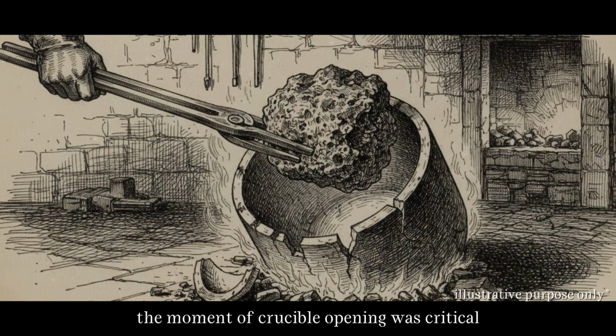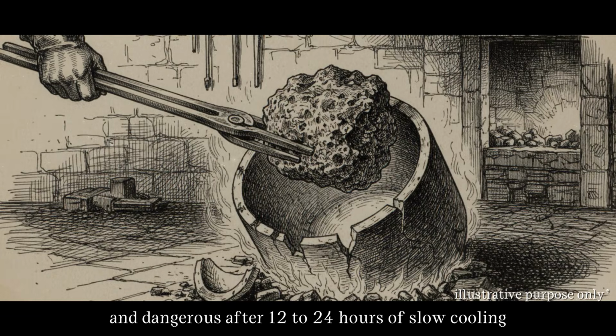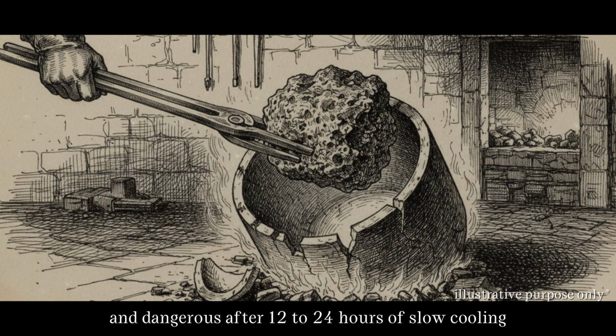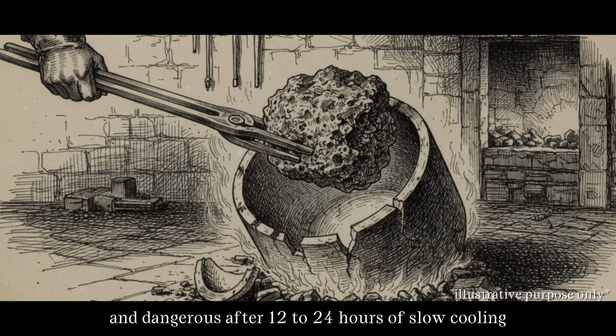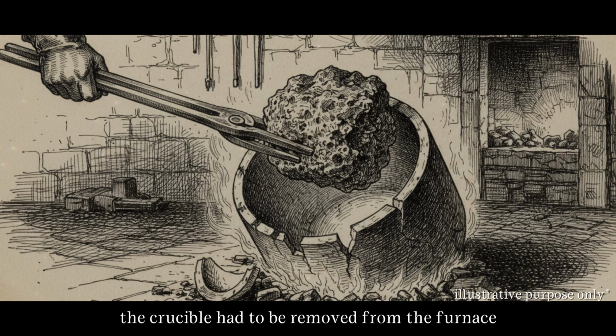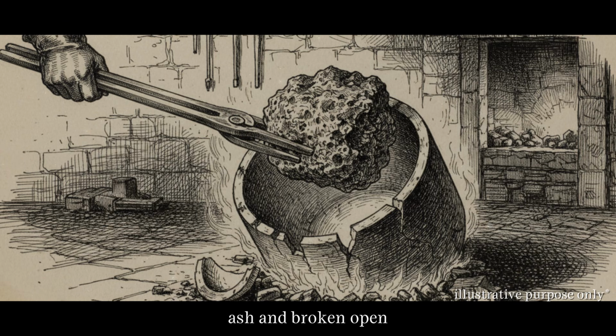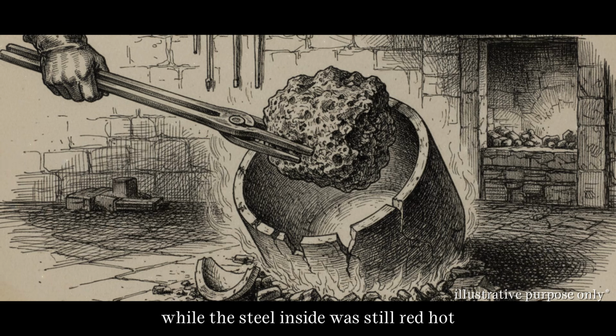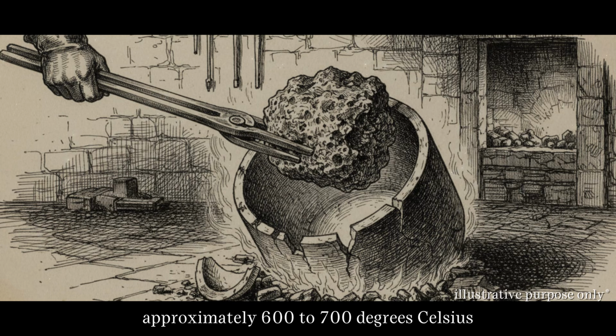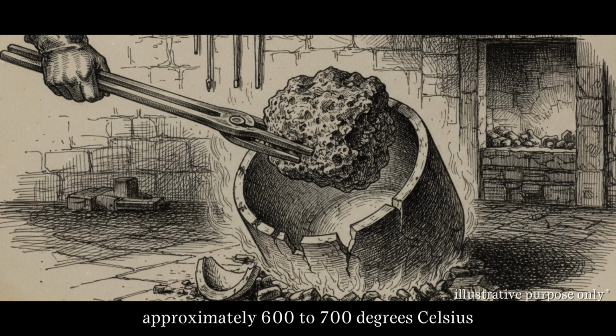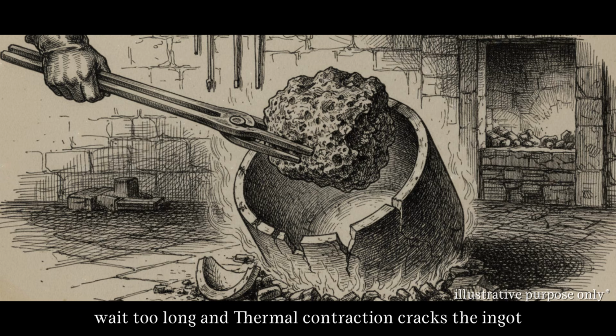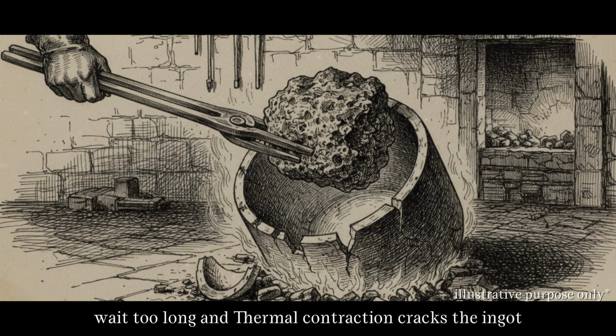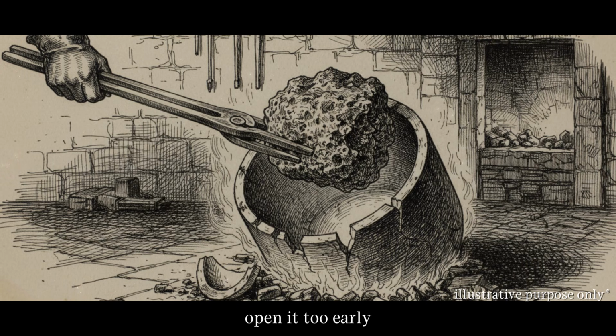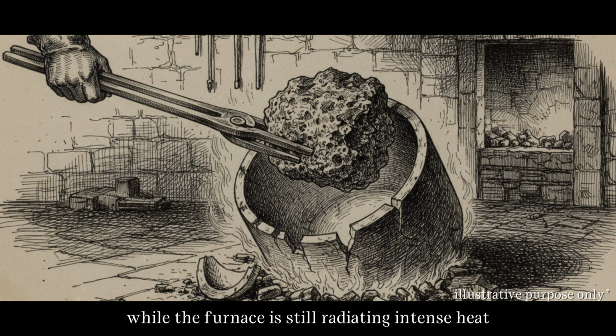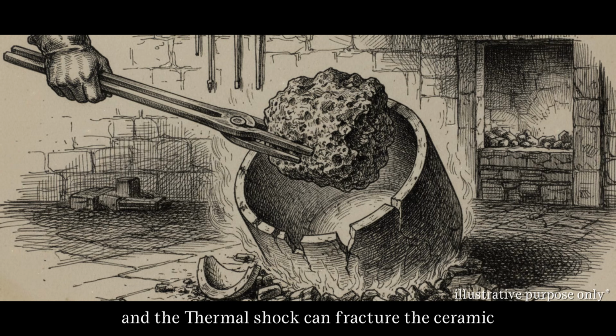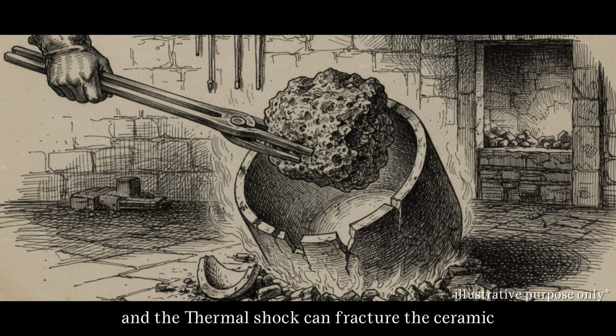The moment of crucible opening was critical and dangerous. After 12 to 24 hours of slow cooling, the crucible had to be removed from the furnace ash and broken open while the steel inside was still red hot, approximately 600 to 700 degrees Celsius. Wait too long and thermal contraction cracks the ingot. Open it too early while the furnace is still radiating intense heat, and the thermal shock can fracture the ceramic.